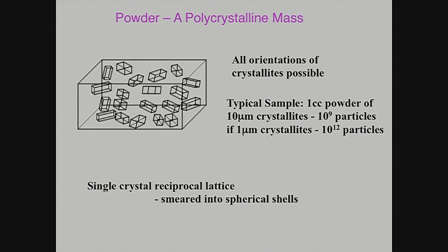And so what you can do is then take that, throw away the intensity outside the unit cell, and then Fourier transform back into Q space and use the phase factors you get from that in an iterative way to solve this. It's extremely computer intensive and was done for the first time less than 10 years ago.